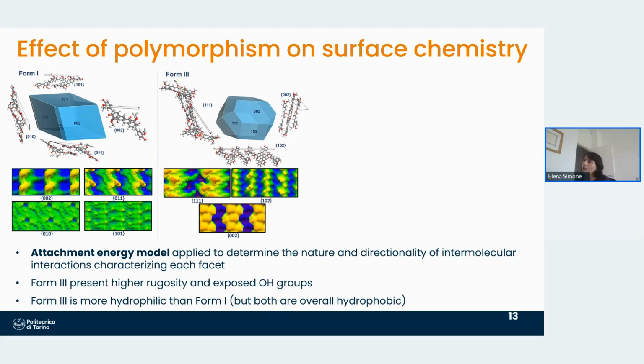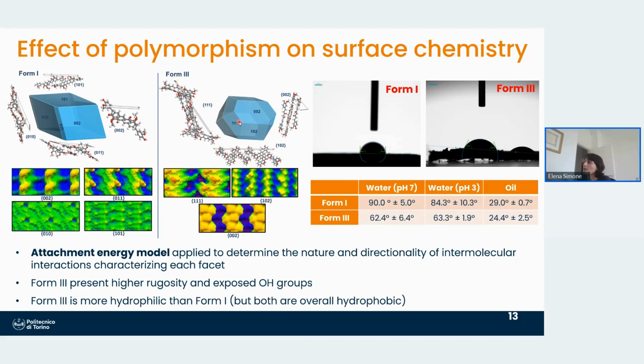What we noticed was that, so we did the same kind of analysis that we did for quercetin DMF, and form 3 was significantly rougher compared to form 1, and also all the different facets were exposing OH groups more frequently. So we thought, okay, maybe this form 3 is a little bit more hydrophilic. And indeed, when we actually look at the contact angle, we found that form 3 was a little bit more hydrophilic compared to form 1.